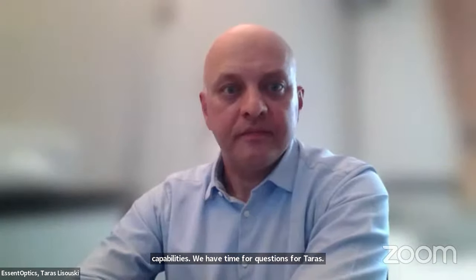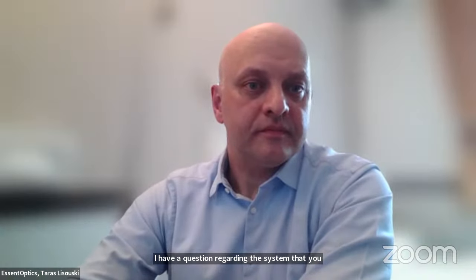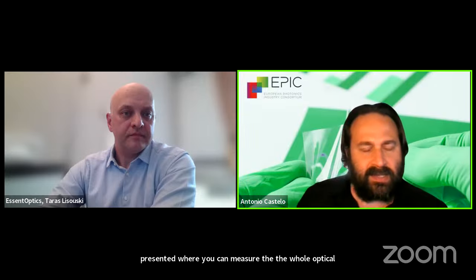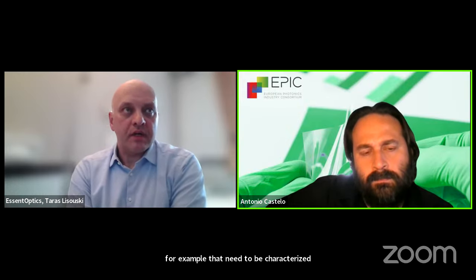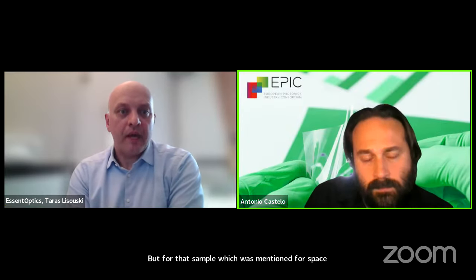I have a question regarding the system that you presented, where you can measure the whole optical system. What's the size they can admit inside? Or can you work on customized solutions if somebody has a big optical head, for example, that needs to be characterized? The smallest sample we were able to measure as standard was 4 by 4 millimeters. The biggest size was 150 millimeters. But for that sample, which was mentioned for space application, the actual dimension was 700 microns. So we were able to generate a beam spot on that sample as small as 400 microns. And we were able to measure these narrow bandpass filters extremely well, surprisingly well, to be honest.